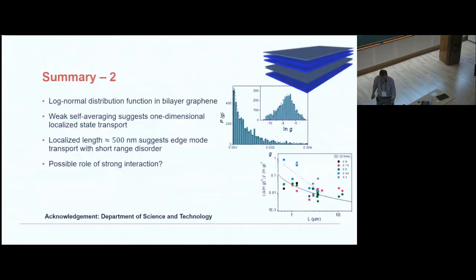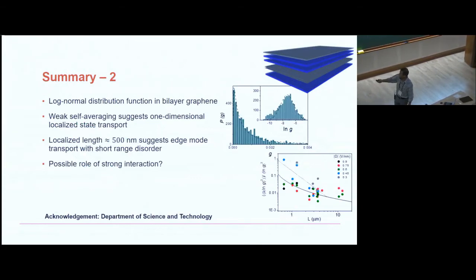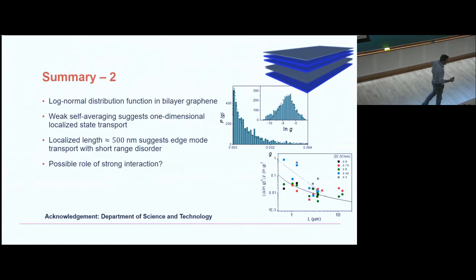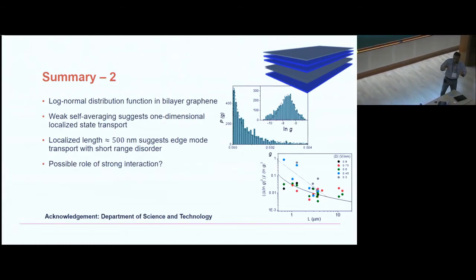So what I would like to summarize in this part of the talk is that we have looked at weak self-averaging, where the log of conductance fluctuations to mean ratio decreases very slowly as you change the length of a bilayer graphene sample, which is one of the most distinctive effects of a 1-dimensional system rather than a 2-dimensional system that you might think. Okay? The localization length is nearly 500 nanometers, even though the gap-induced localization length cannot be more than 5 to 10 nanometers. And hence, the localization length is not governed by anything to do with the gap or the electric field we apply, but probably by the large amount of disorder along the edges.